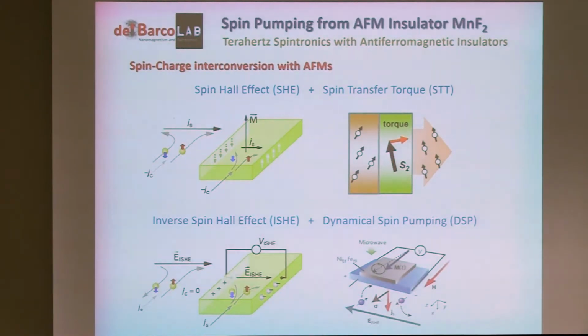Well, there are many tools that you can employ in spintronics. Two of the most used ones are here. One is the spin Hall effect, that is basically driving some charge current through a material with high spin-orbit coupling to separate the spin polarizations of the conduction electrons into the two sides and as a result, you will generate spin current in one direction. That is orthogonal to the charge current and orthogonal to the effective magnetic field that you will get there, that is basically coming from the spin-orbit coupling. Well, this basically, from charge current, you generate spin current.